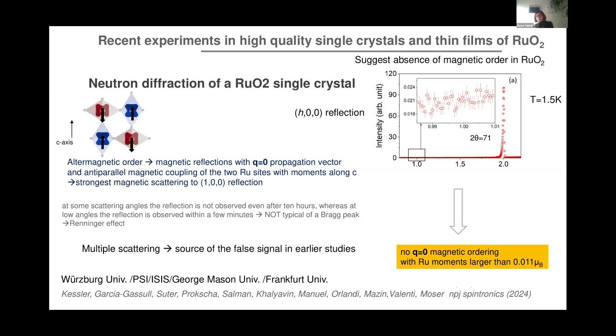However, if they go to very low angles, what they observe is indeed some signal, but only within a few minutes. And it seems, and the neutron scatterers are the experts on that, that this is not typical of an observation of a Bragg peak. It has in fact a name. This is called the Renninger effect, which indicates that what one is observing here is effects of multiple scattering.